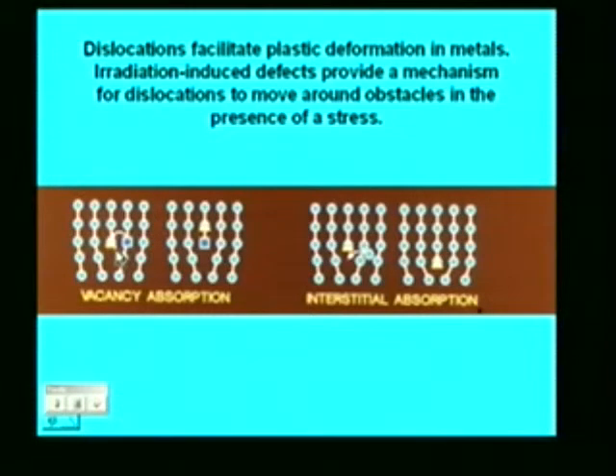And if we want to shear that metal, if we didn't have a dislocation there and we wanted to put a stress on this plane with respect to the one above it, we'd find we had to break all these bonds. But if we had a dislocation, we can break one bond at a time, and the dislocation will kind of flip over and move to the edge. And metals commonly plastically deform.